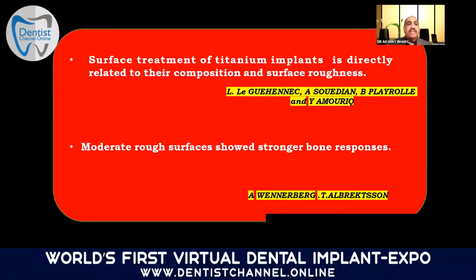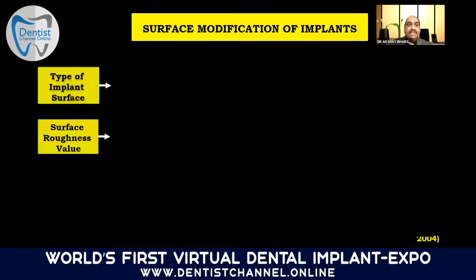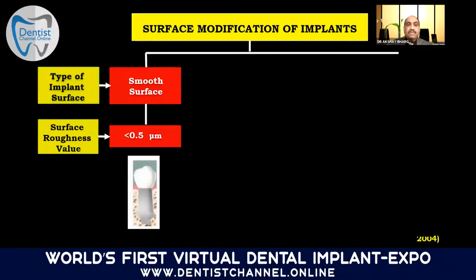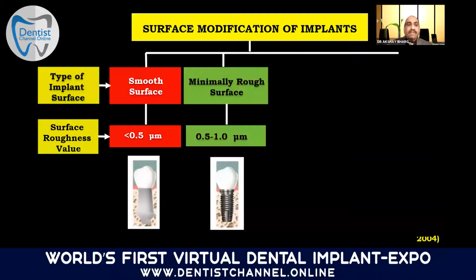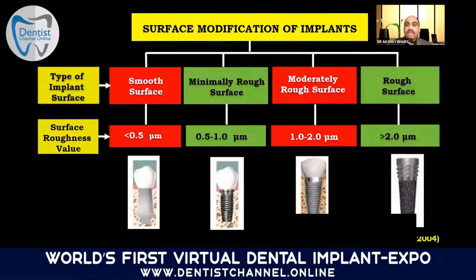Surface treatment, this is a brief history. The surface treatments of titanium are directly related to its composition and roughness. Moderate surfaces show stronger bone responses. The surface modifications generally seen, by type of implant surface, you have smooth, minimally rough, moderately rough, and of course the totally rough surface, ranging on a scale from less than 0.5 microns to greater than 2 microns. This is how you could probably classify the surface modifications in implants.